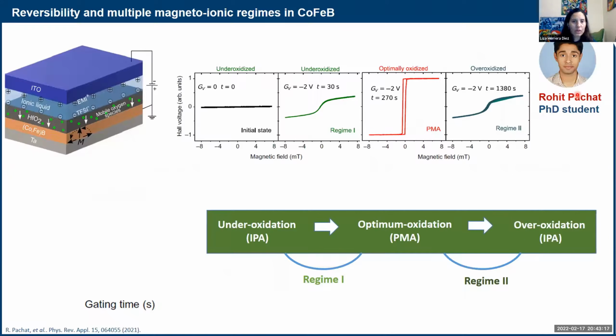So the last thing I wanted to show you from our results is our measurements on tantalum, cobalt iron boron, hafnium oxide. So here we can see the full spectrum of the oxidation. So then we could go from an under-oxidized state, which was the initial state. Here, once again, we come back to amorphous films. So the initial state has in-plane anisotropy. And then we go little by little to the PMA state, and then we overdo it. Then we just keep adding oxygen, and then it goes back in plane. Then we have this full transition that you can see here. And then we call the first one regime 1. So basically in plane under-oxidized to PMA, and then PMA to in plane over-oxidized, regime 2.